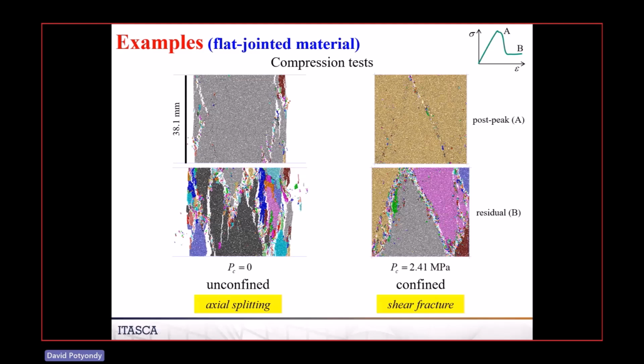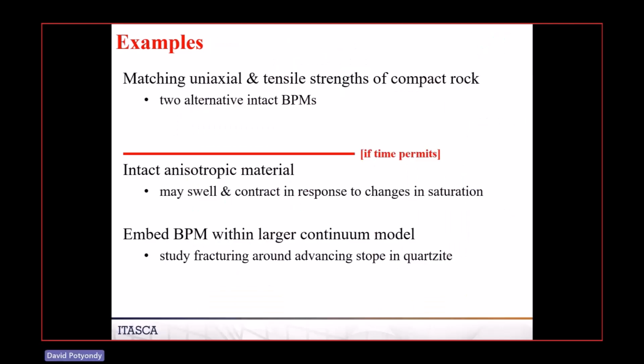In the 3D flat jointed material, you basically get distributed damage of pencil cracks throughout the material. And then once you get near the peak, you get a small number of shear cracks that form and the specimen then will fail. So that's the flat jointed material. This is a demonstration of the fact that you can build a grain-based material and really get great behavior in detail. If you do a grain-based material with no breakage, you're basically getting a similar type of response to a flat jointed material, which of course requires far fewer particles. Just a few other things to show here.